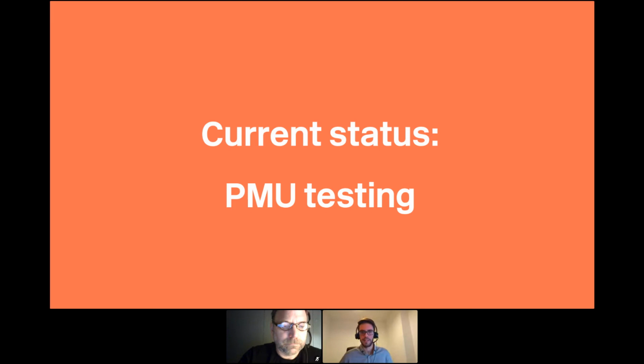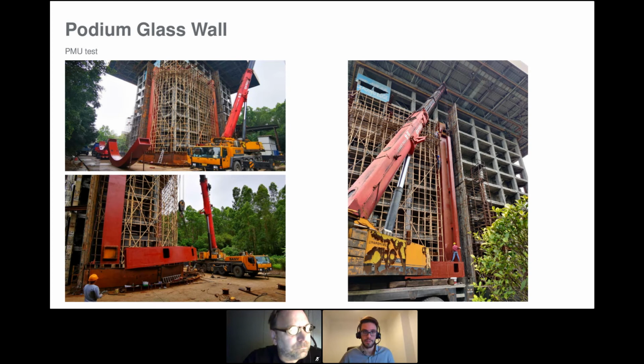But we have also a few pictures to show for the PMU test, which were kindly shared by GNM, the contractor, as for obvious reasons we couldn't travel and assist at the test. But the coordination we had was very good, because we had a very collaborative interaction, trying to understand all the steps and making sure that every step of the installation, the pretensioning and all the tests were in line with what we expected from the analysis we ran, to make sure that all the results were consistent and we were going in the right direction.